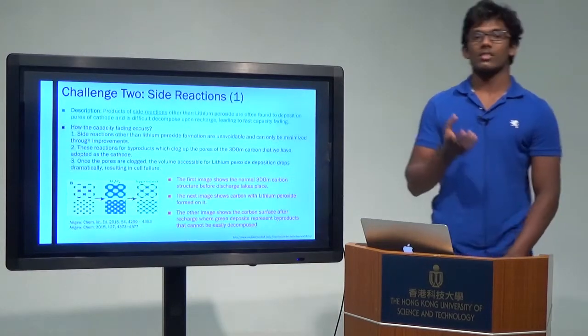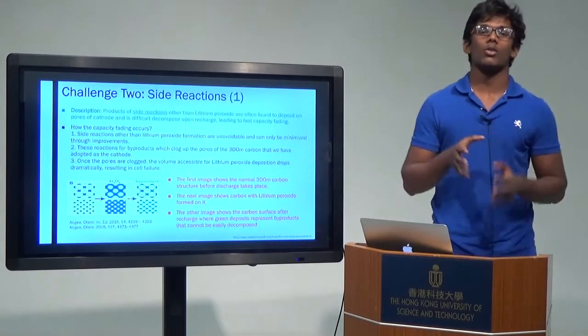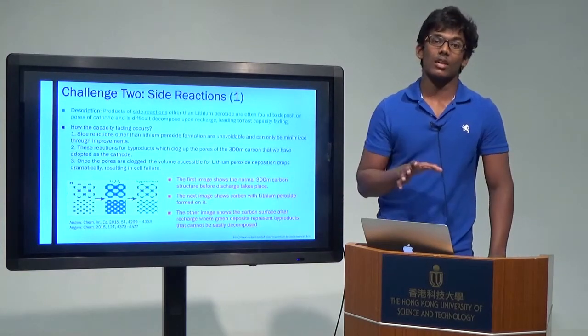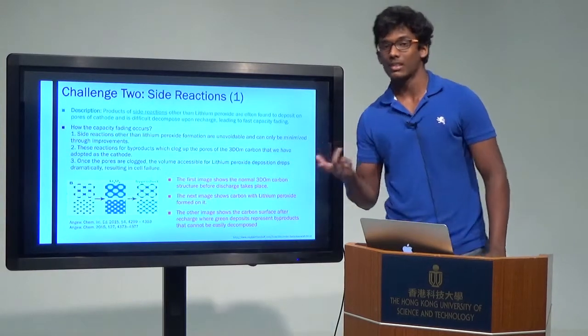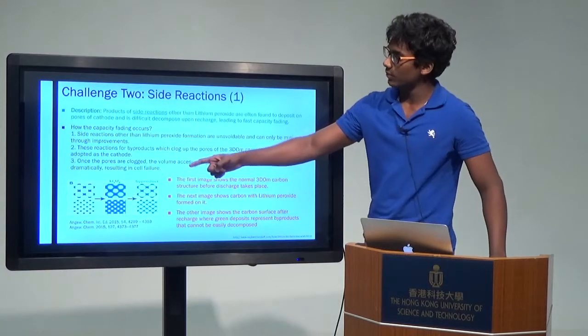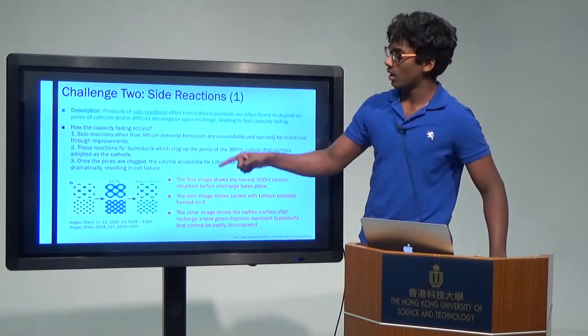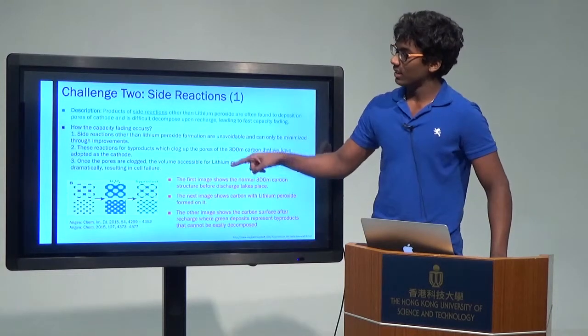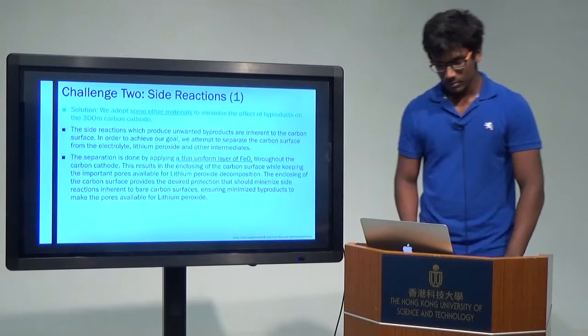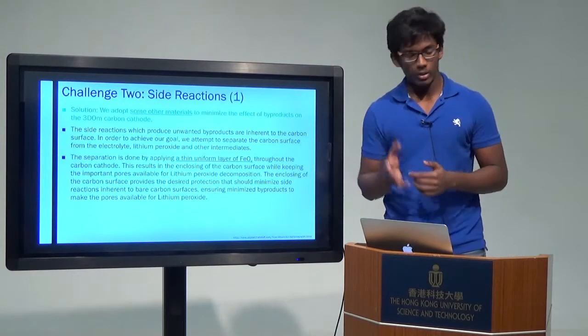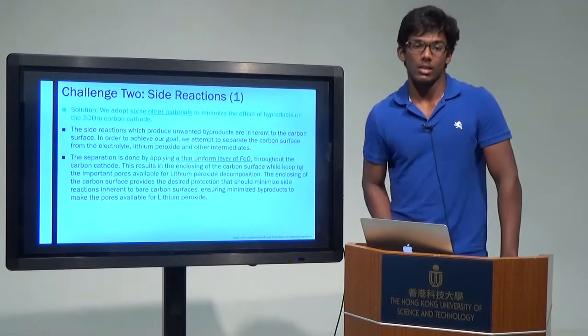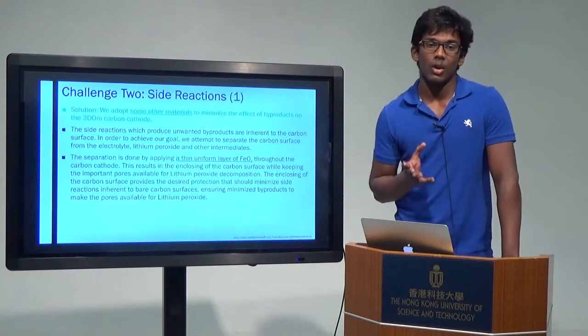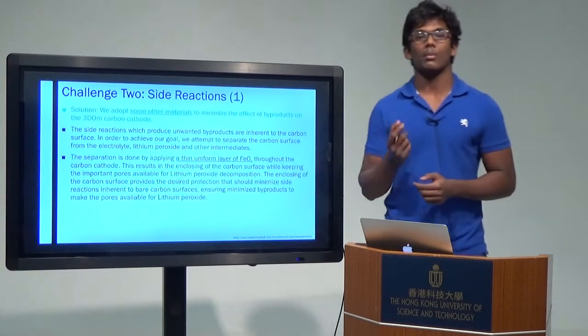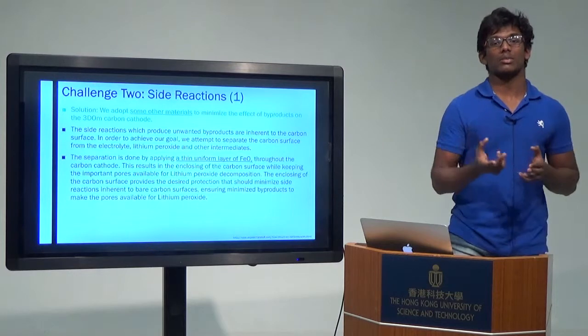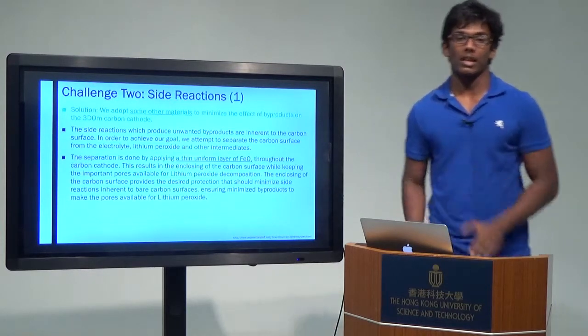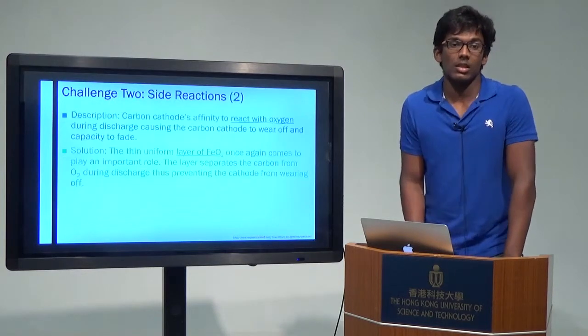Another challenge is that the products of the side reactions, other than lithium peroxide, are often found to deposit on the pores of the cathode and are difficult to decompose upon recharge, leading to fast capacity fading. As you may see, there's a bare carbon surface, a surface with lithium peroxide deposited on it, and then the surface with byproducts clogging up the pores. What we have done is applying a thin uniform layer of iron oxide throughout the carbon cathode. This results in the enclosing of the carbon surface while keeping the important pores available for lithium peroxide decomposition. The enclosing of the carbon surface provides the desired protection that should minimize side reactions inherent to the carbon surface.